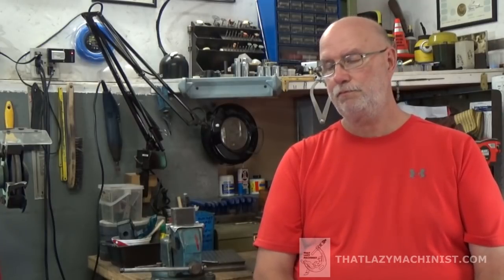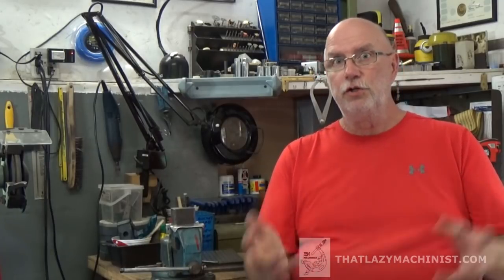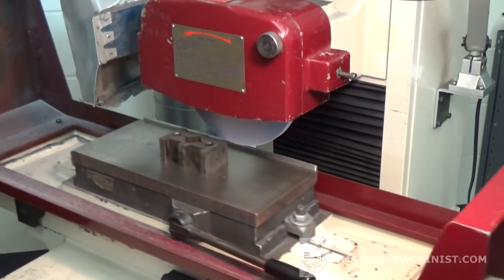But I want it to deform the least possible because I want to grind it the least possible to finish it. So I'm going to rough the part out, leaving a certain amount on it, and we saw that in our 1, 2, 3 block project videos. And then I'm going to heat treat it, and then I'm going to go to the grinding and grind it to its final, very, very accurate dimensions once it's hardened. But I do want the least amount of deformation possible. So I use an alloy carbon steel. If I have, again, I'll come back with the 4140, I could have chosen O1 steel as well, oil hardening class 1 or a tool steel.